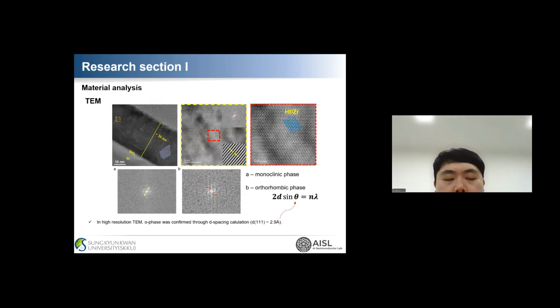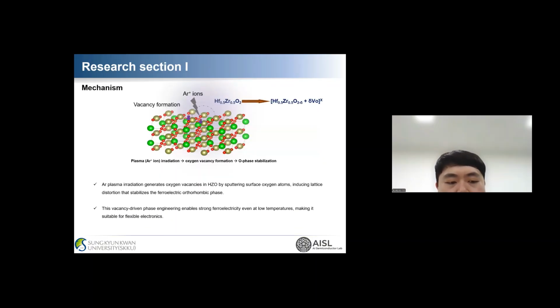We also performed TEM analysis to investigate the crystallinity of HZO. From the TEM image, we confirmed that HZO is polycrystalline rather than single crystalline. Minor grains corresponding to monoclinic and tetragonal phase are observed. However, most grain regions exhibit the orthorhombic phase, which is responsible for ferroelectricity. The lattice spacing of the orthorhombic phase is measured to be approximately 2.9 angstroms, and this pattern is widely observed across the TEM image.